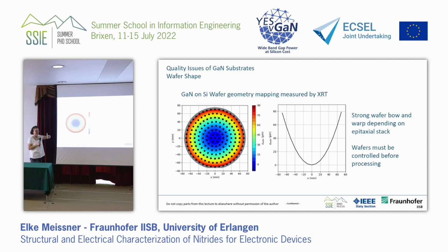This is also true not only for native gallium nitride and aluminum nitride wafers, this is also true for gallium nitride on silicon, because of course you put this big epistack on it, and if you put this big epistack on it, the wafer gets bowed, because you have material with different matching in terms of structure and thermal match, and then the wafer gets bowed. And you see that this is a larger wafer, but the wafers must be controlled before the processing, because if a wafer is such bowed, you have maybe like 80 micrometer bow, or you have 100 micrometer bow. If you put an even thicker layer, the wafer either breaks, or you cannot put it to a processing anymore. So your wafer stepper will not take it. Or at least the person who's operating the wafer stepper will say, go away with this thing. So you cannot operate it as long as it doesn't stay flat.